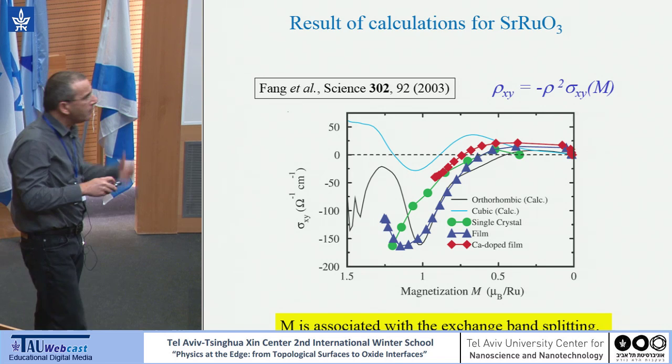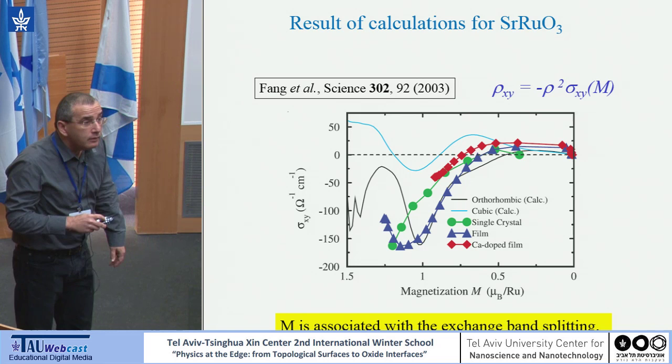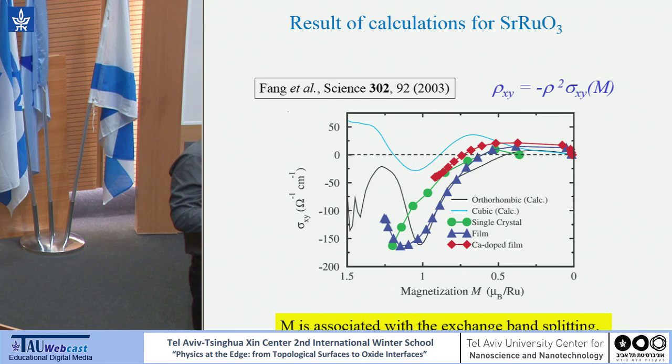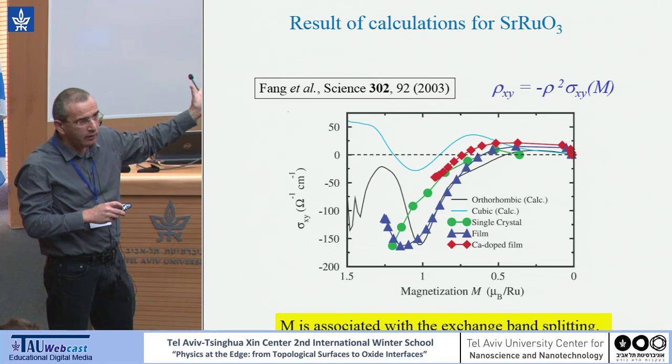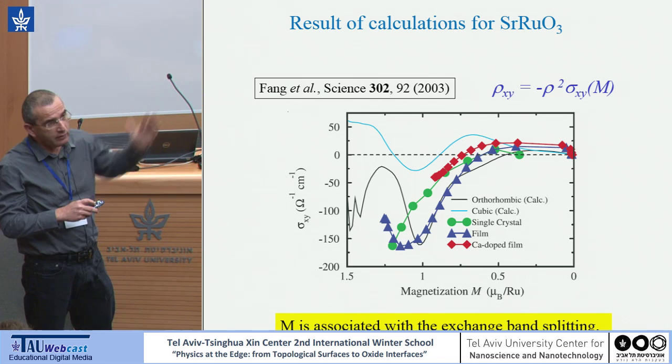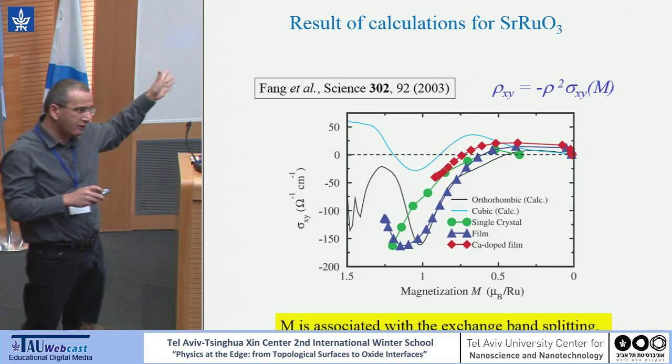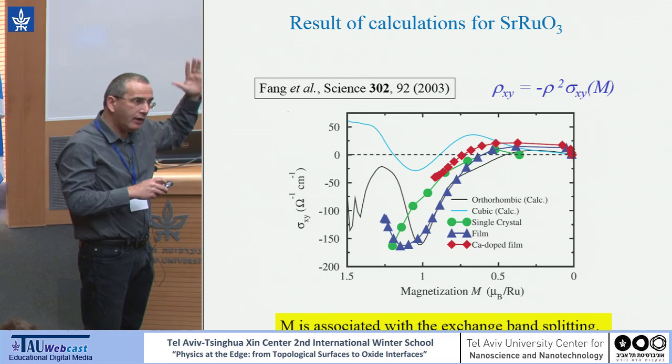At what temperature is the spin reorientation? I didn't talk about it, but the spin reorientation is a transition in which the direction of the uniaxial axis goes from 150K, which is TC, down to a zero temperature limit. The direction of the magnetic moment changes by 15 degrees, at the rate of 1 degree per 10 degrees Celsius. So this reorientation transition is not relevant to this study, but there is a very gradual change in the direction of the uniaxial magnetocrystalline anisotropy.